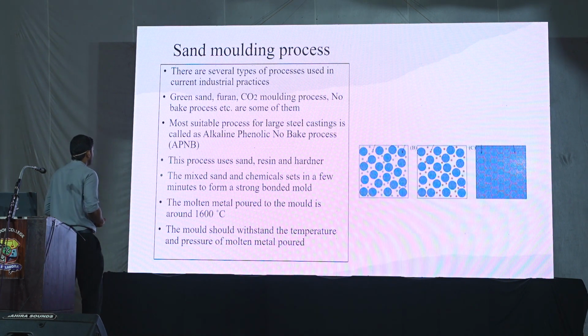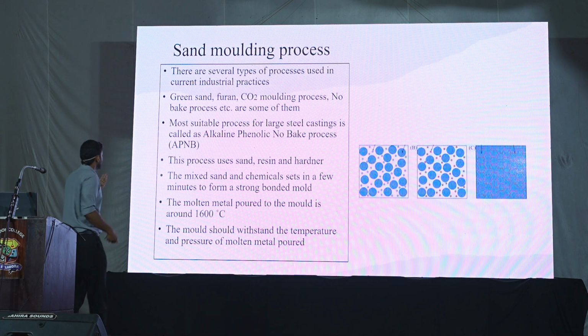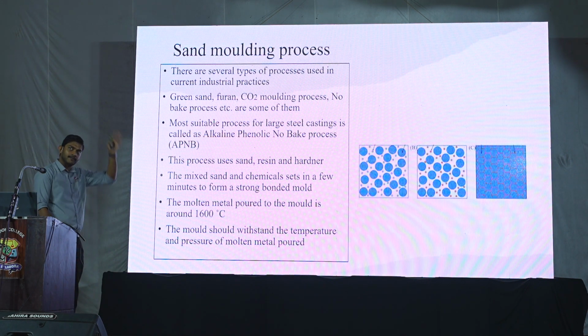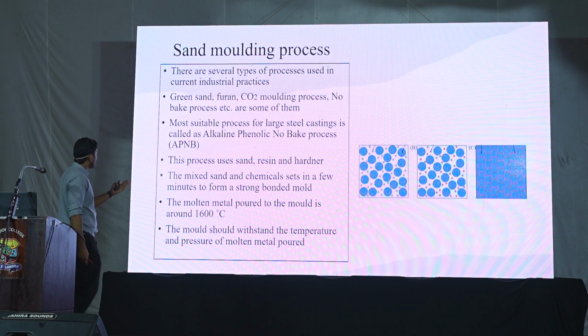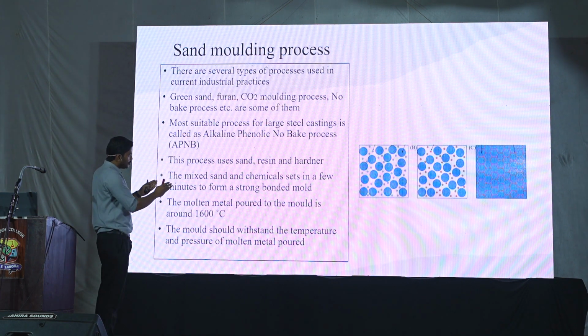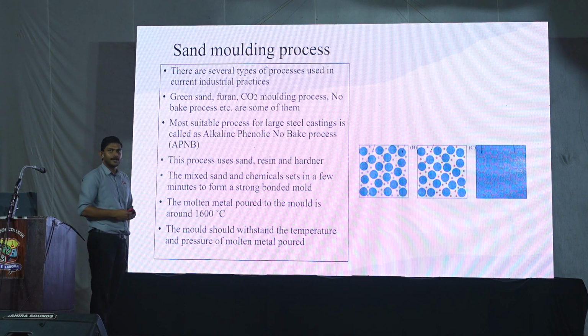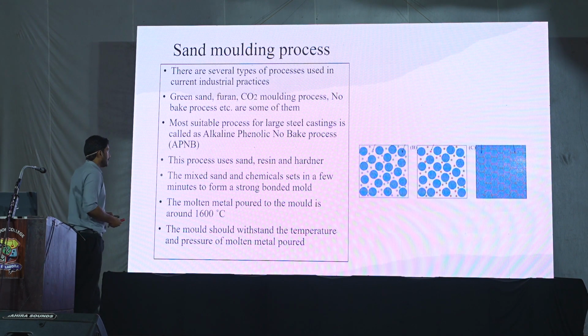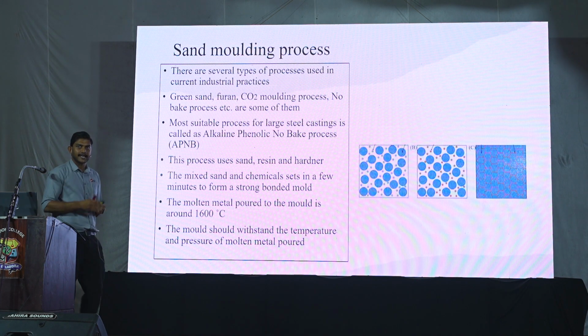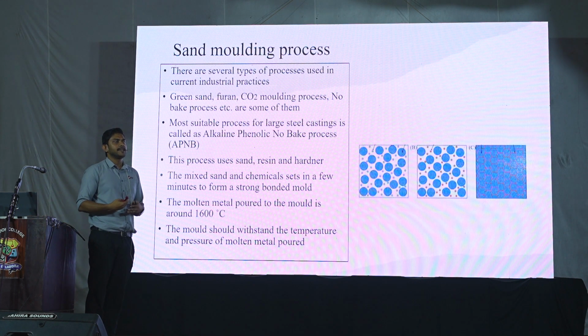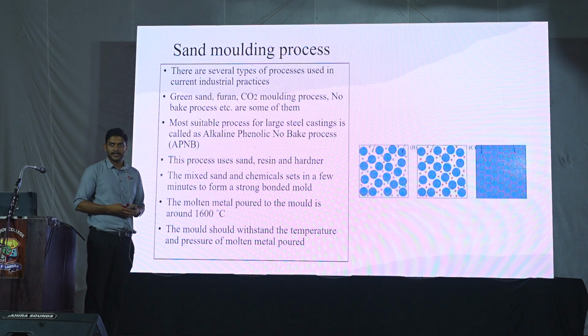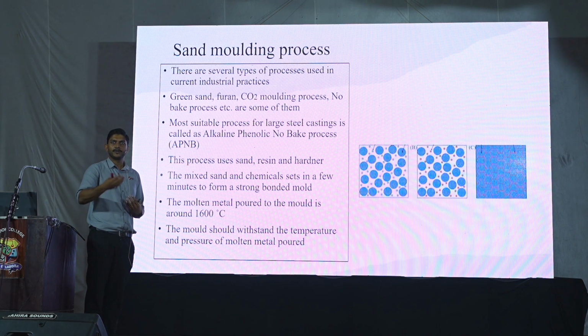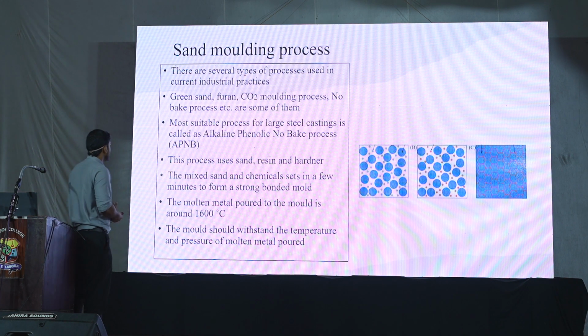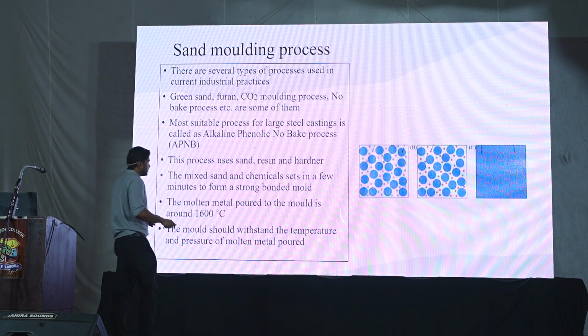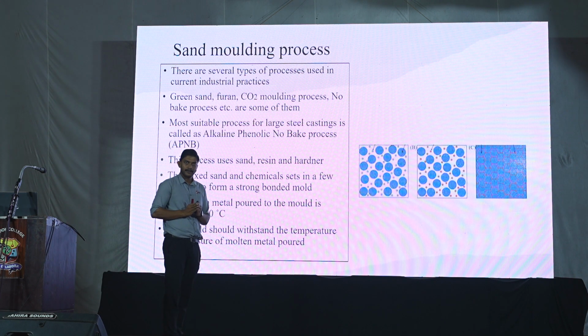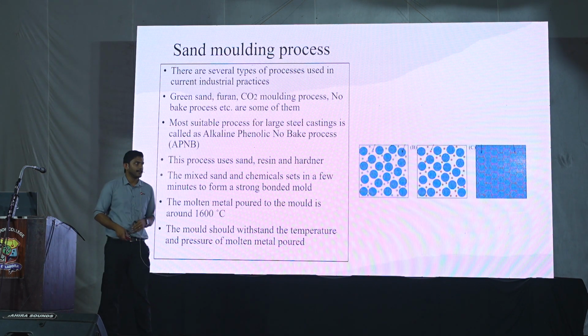So basically, the mold making process can be classified into several types. We have green sand, which is the conventional age-old process, furan CO2 molding process, and no-bake process. What we use is called the alkaline phenolic no-bake process, which is suitable for medium-sized to large-size castings. Medium size, we can say as 500 kgs to 1000 kg, and large, we can say 20 to 25 tons, or 25,000 kilograms. So at that scale, this should work pretty accurately. Otherwise, you'll collapse everything, you'll lose the quality of the product.